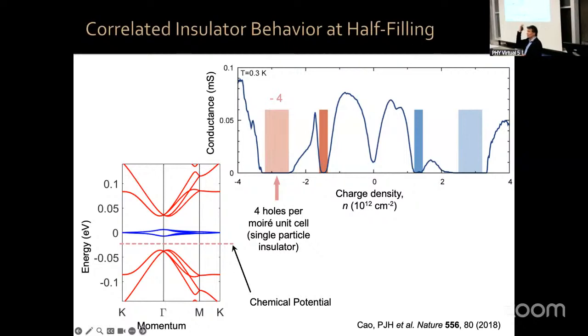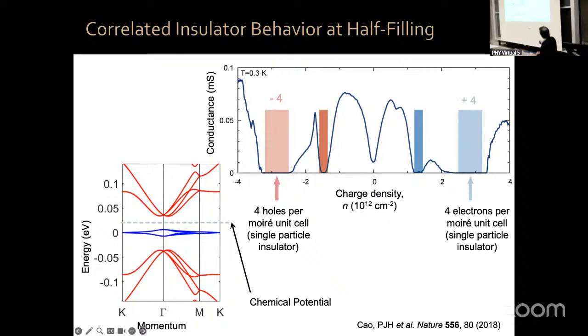Again, this number 4 has to do with this spin-valley degeneracy thing I mentioned earlier. So if I put 4 electrons per moiré unit cell, my chemical potential sits in the middle of this band gap, and therefore I have single particle insulating behavior. That behavior is easy to understand. It was predicted, and in reality interactions modify this, but to zeroth order it's quite simple to understand.